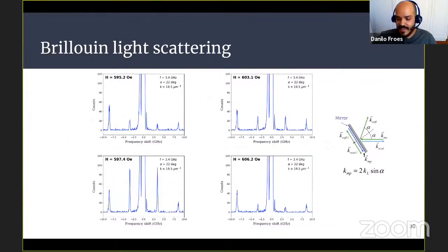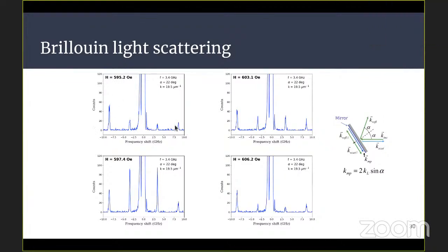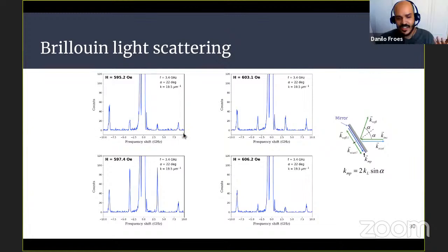For the LPE, the low damping sample, we used Brillouin light scattering. Again, we fixed the alpha, the incidence angle, so I fixed the excitation k, the wavelength, and we took the spectrum by varying frequency and magnetic field. For each field, we did an experiment. We have these peaks around 8 gigahertz that do not change with the frequency. They are thermal magnons that are being excited.